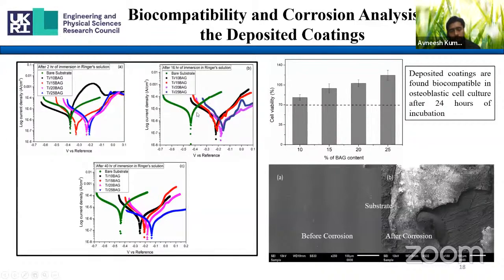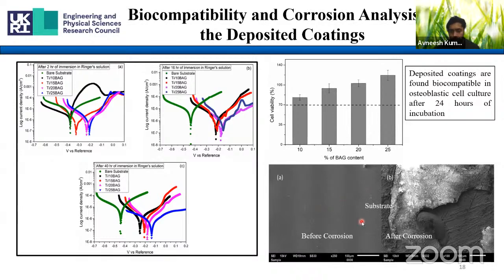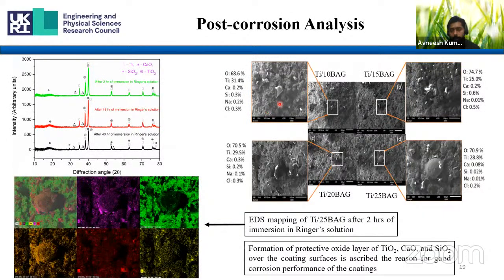To see how this coating is performing well, we did some post corrosion analysis also. Here you can see the substrate before and after corrosion. Before corrosion, this was the substrate. After corrosion, you can see how it gets deteriorated. Even the top layer of the substrate has peeled off. Then we also did some SEM and EDS analysis of the corroded coatings to see what is happening on the surface, and we found that in all the cases, oxygen content has increased immensely.